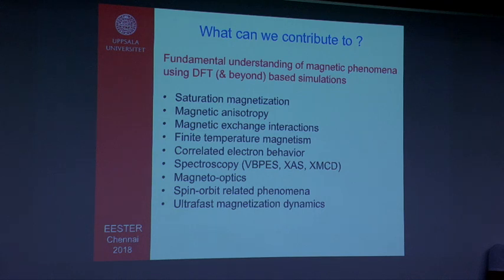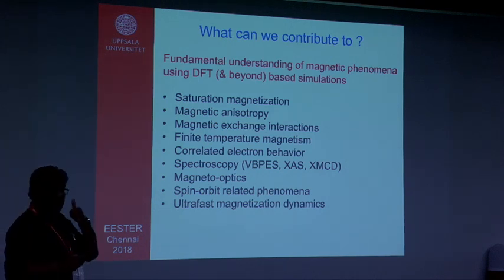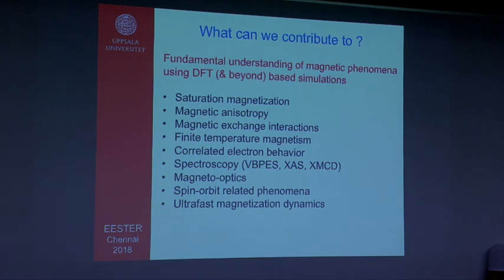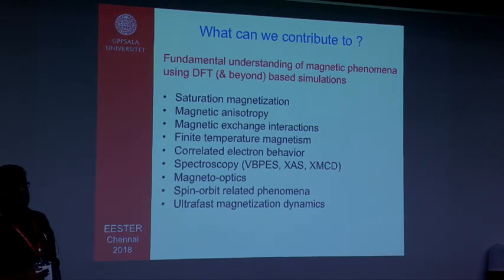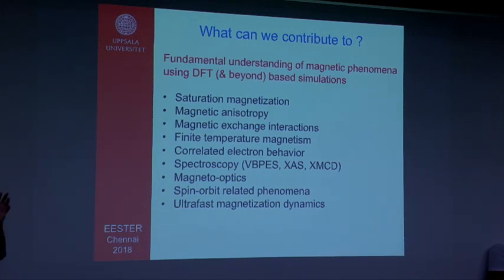Saturation magnetization, magnetic anisotropy, which is basically related to spin orbit coupling. Magnetic anisotropy is another very important thing because that can tell you whether a material has a perpendicular magnetic easy axis or an in-plane magnetic easy axis, and that is extremely important not only for the experiments, but also for the technology, for the devices. Of course, magnetic exchange interactions, these are very important because that gives us the idea whether the local magnetic moments you have in your system are going to interact with each other at a finite temperature, at a temperature that we want them to interact, let's say at room temperature, whether that will happen or not.